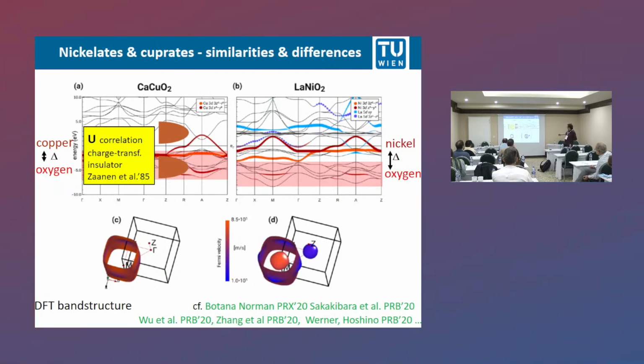But then it's also closer to the lanthanum or neodymium bands, and that you see here at this A and gamma momentum, these bands cross the Fermi level and give rise to this gamma and A electron pocket. So you have in DFT a mixture of a hole-like Fermi surface and 2 pockets that you have here. Now Frank will talk more about the z² orbital that is lower in energy in the cuprates. In the nickelates, it's somewhat closer to the Fermi energy.